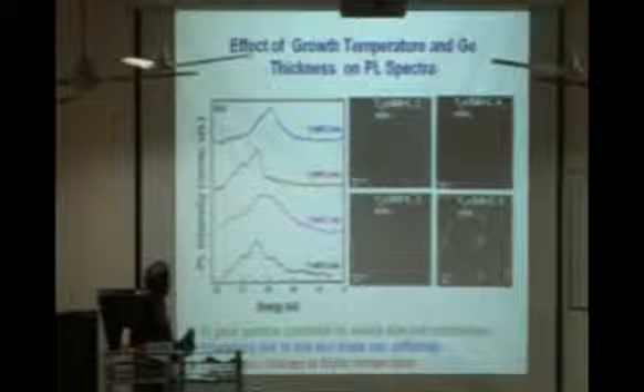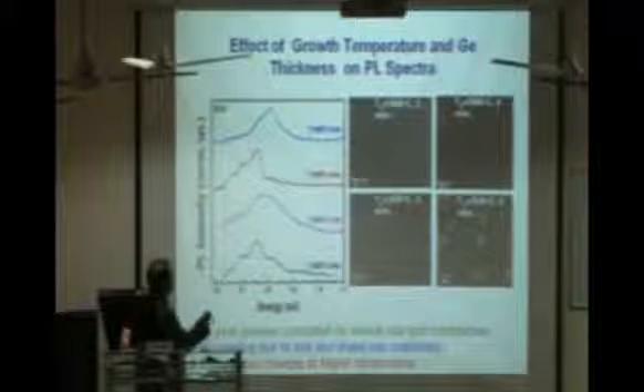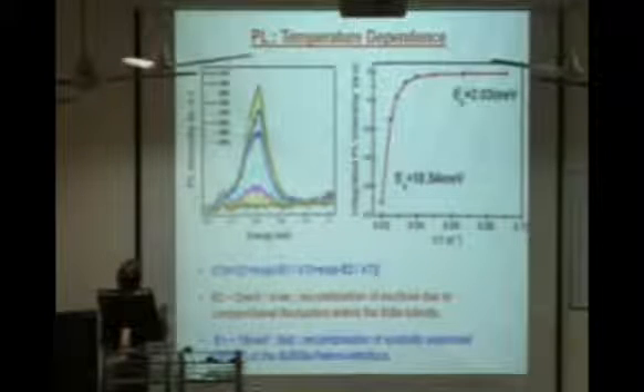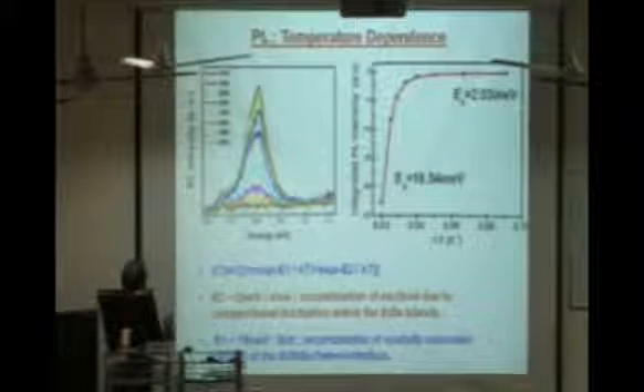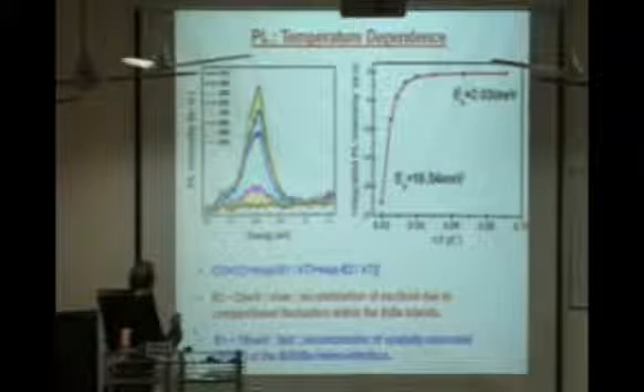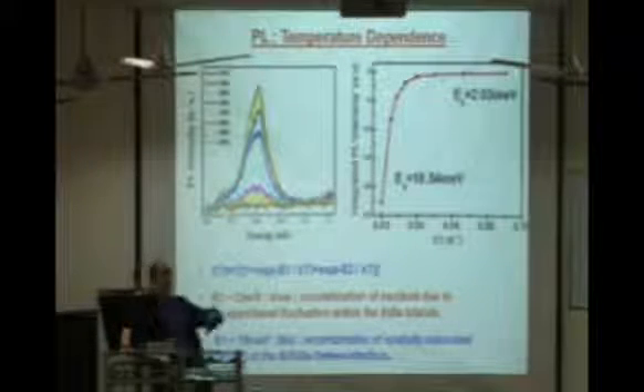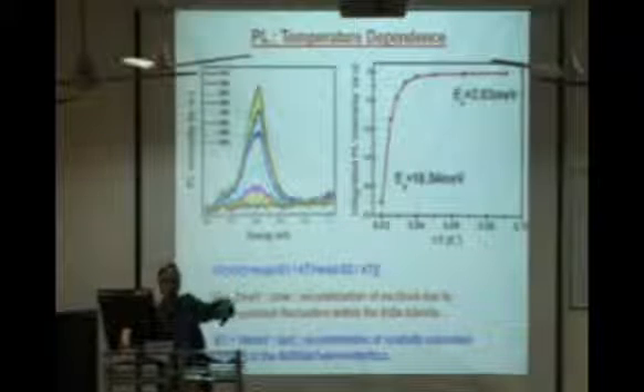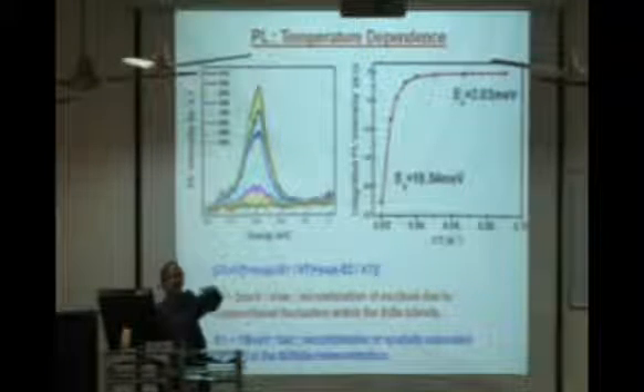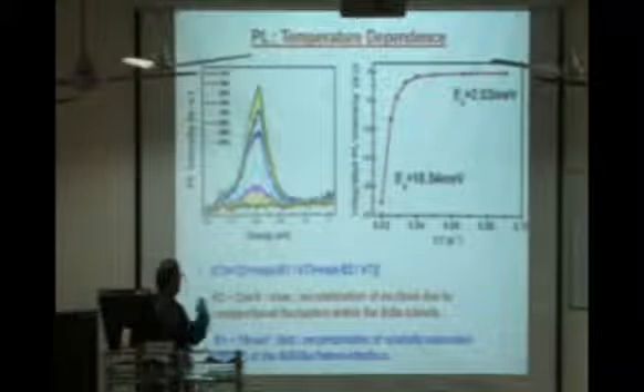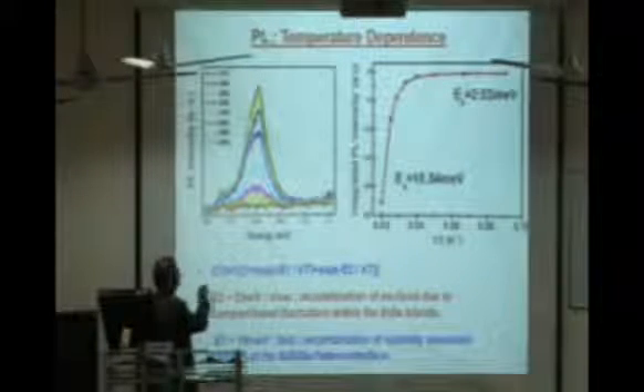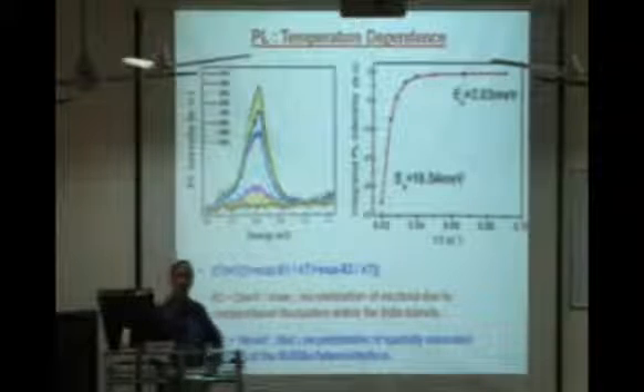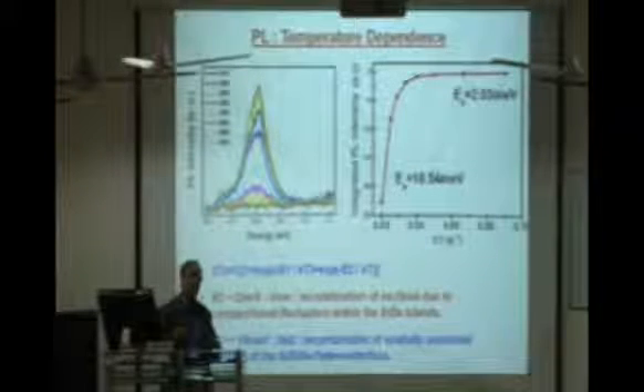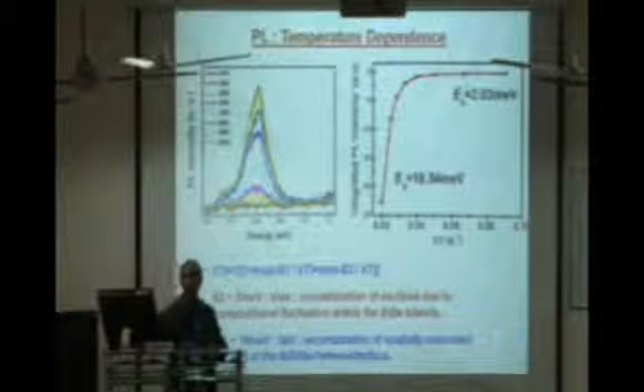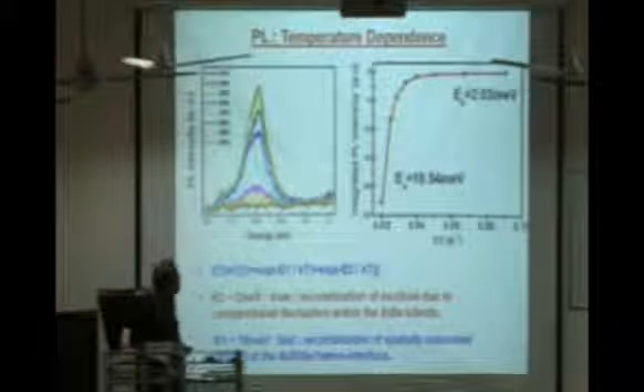We get that. Only thing, as you see, this is very broad because of the size distribution of those quantum dots. In fact, this luminescence typically exists only up to about 40 Kelvin or maximum 50 Kelvin, because the exciton binding energy is very, very low. If you take this system to higher temperature, the excitons break, and ultimately you get quenching of the luminescence. That shows this is only good at low temperature. But the question comes, can we really achieve this emission at room temperature or near room temperature? Then definitely they will be very useful.